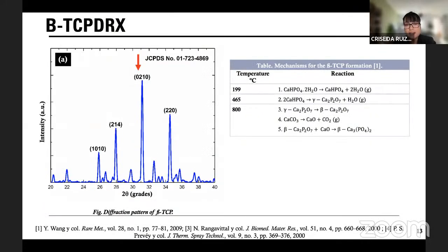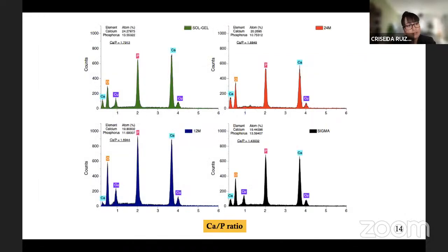Then X-ray diffraction verified the crystalline phase formation. This diffractogram corroborates the formation of beta-tricalcium phosphate due to the chemical reagents reaction in the solid-state process. The calcium to phosphorus ratio in atomic percent was corroborated by EDS. These powders show ratio values from 1.4 to 1.8. This data indicates the calcium phosphate type, which allows us to analyze and understand the dissolution of the powders in contact with body fluids.